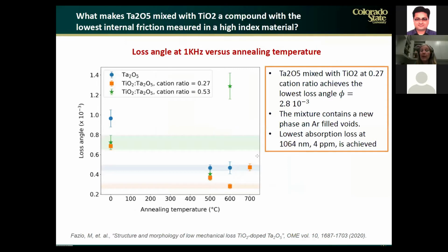So we conducted loss angle measurements on these materials with the technique that I showed you before. And what we learned is that in both cases, the two alloys reduce, this is shown here by the orange and green points, the two alloys reduce the mechanical loss of tantala. This is the loss angle of tantala as deposited film.